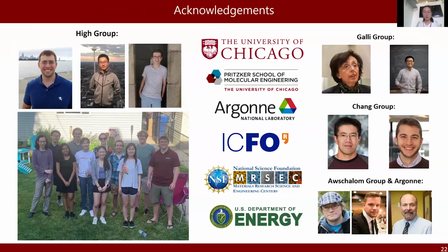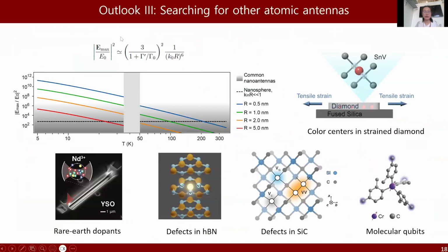Yeah, that's a great question. If we take a look at this formula, this near field enhancement really depends on the ratio between this gamma prime and gamma naught, which means that we need to have a very coherent optical transition, and this condition can be satisfied by many quantum systems. So besides color centers such as the germanium vacancy center, there are also a lot of other systems such as rare earth dopants, defects in hBN, defects in silicon carbide, and a lot of molecular qubits.